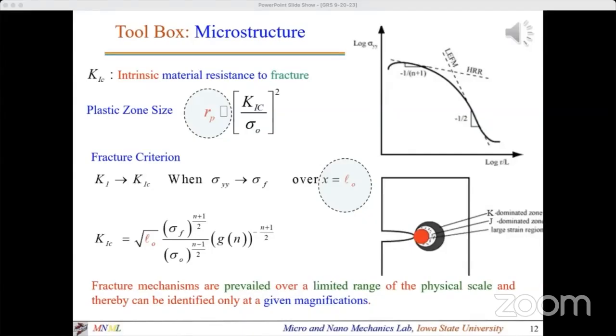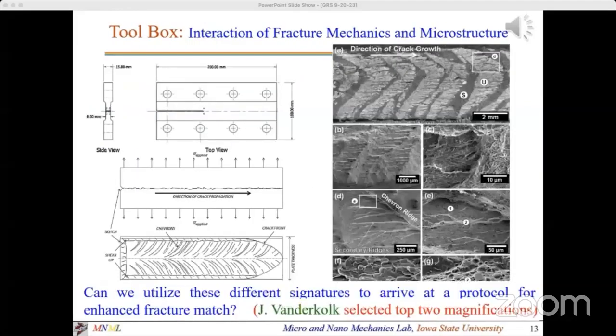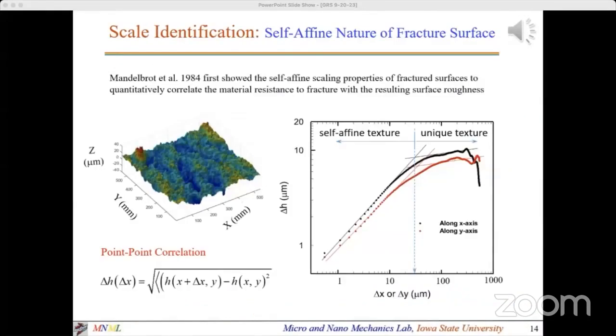Accordingly, fracture mechanisms prevail over a limited range of the physical scale and thereby can be identified only at a given magnification. Here is crack propagation under tension, viewed with different magnifications. So, which scale should we consider to analyze? We asked our forensic science collaborator John Vanderkolk, and he said we should use low magnification, A and B. At high magnification, C to G, the details of the fracture mechanisms prevail and the topology may not be distinguishable. So actually there is a basis for the choice of the scale.